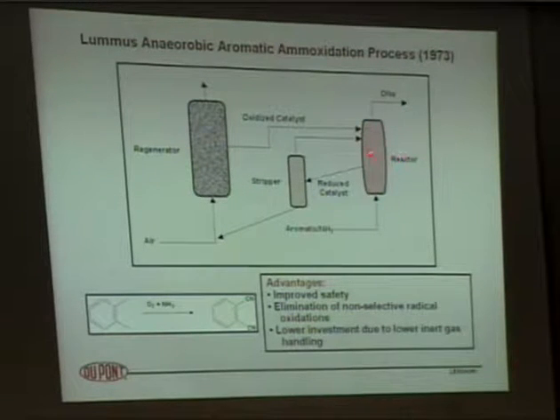The reduced catalyst is then separated, goes off into a small reactor where the adsorbed dinitriles are stripped off, oftentimes with steam or something like that, and they go back into the reactor and are separated. The reduced catalyst then goes through the regenerator where it's reacted with air or oxygen, regenerated, comes back over here and goes around and around and around the loop. This is a pretty nice process.